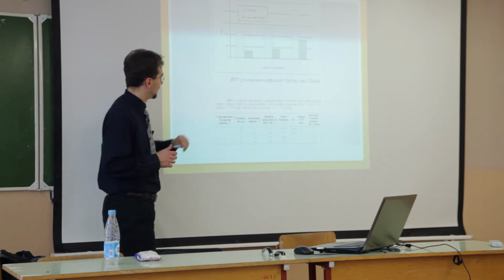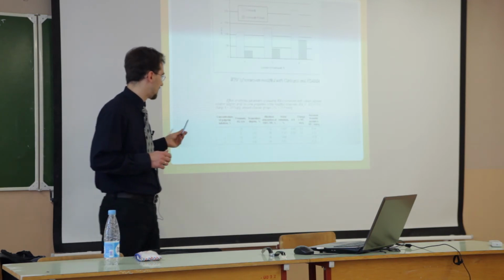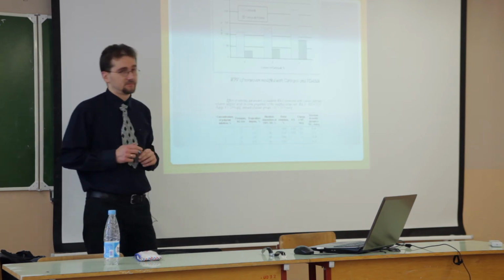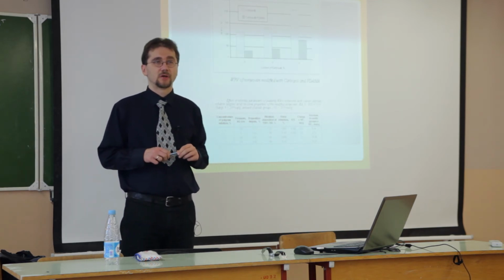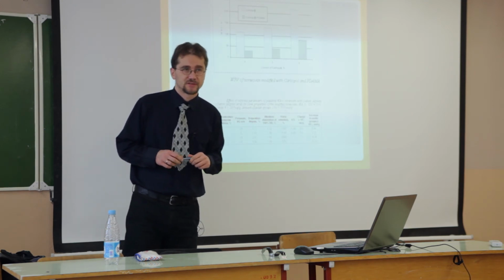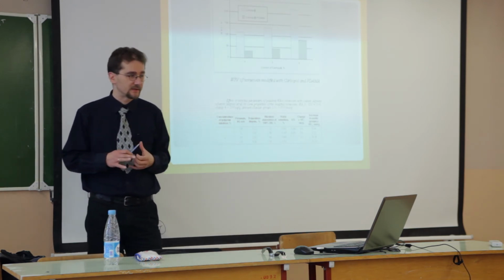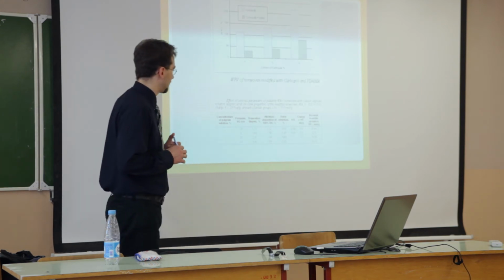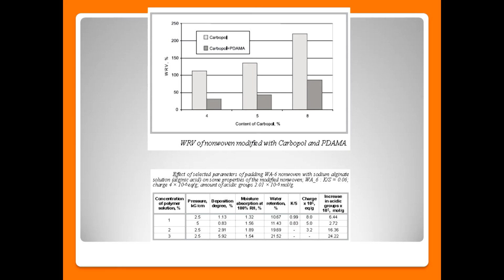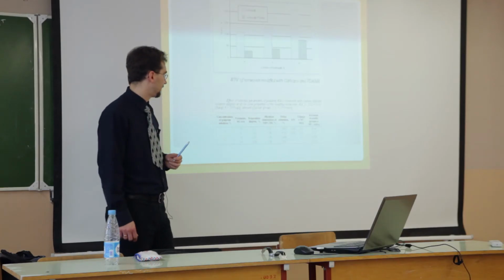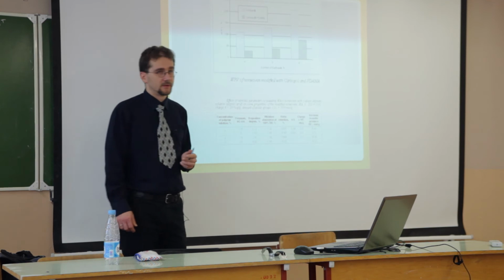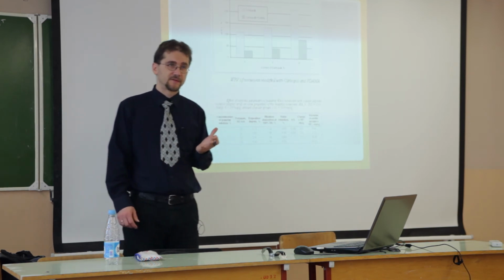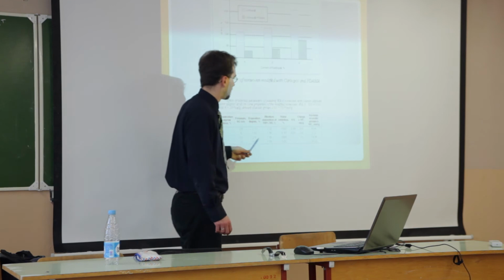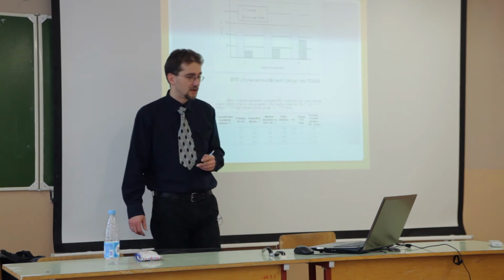Again, about the hydrophilic properties. So we are changing the conditions of the padding reactions, of the deposition of both layers, and finally we received material which can have very different hydrophilic properties, different water retention, different moisture absorption, and different deposition degree. Instead of FTIR spectroscopy, here we calculate the increase in acidic groups on the surface.